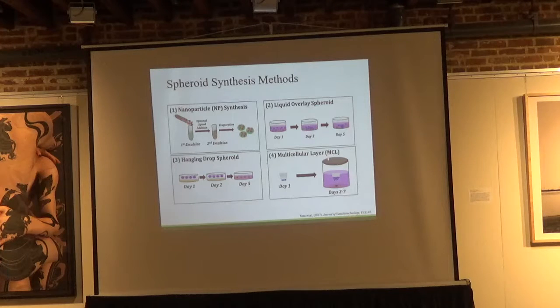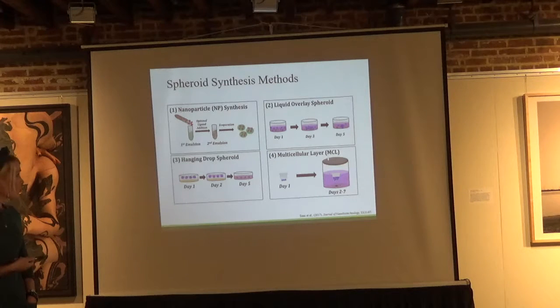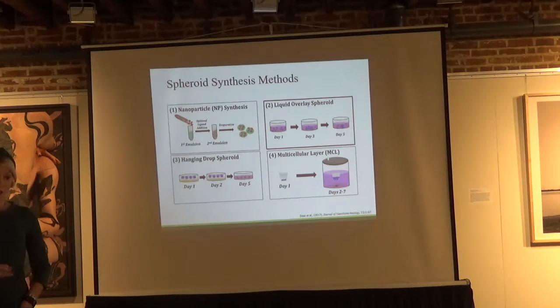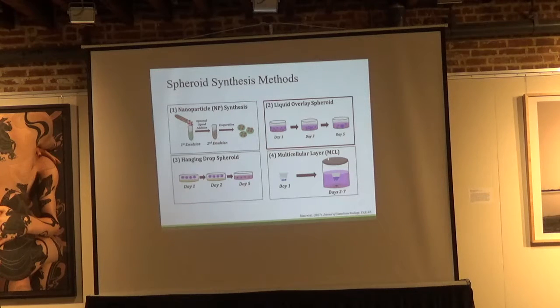But we hadn't looked at them in the tumor microenvironments that we can grow mimics to represent within the lab. So briefly, we formulate our nanoparticles with an emulsion-based process, and then we wanted to look at how different modifications of these particles could penetrate tumor matrices, either using a liquid overlay spheroid, where this spheroid formation method generates rather large tumor spheroids, or the hanging drop method, where you can form very small and more tightly clustered tumor spheroids to represent that cervical tumor environment.